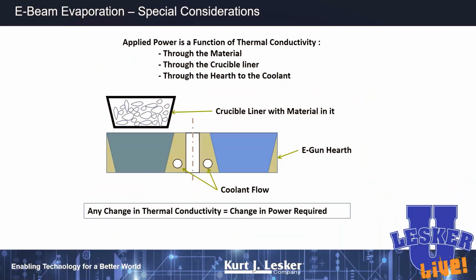Now, for some materials, like platinum and tungsten, maybe tantalum, you may not want your crucible to be in direct contact with a water cooling hearth. So maybe you'll put a small washer down here of graphite or something like that, so that the crucible rests up on top of that washer, and you're not water cooling the crucible. For other things, like aluminum, which is so horrible, you do want it to be in complete contact with the water cooled gun, so that we can keep the aluminum cool and it doesn't spit.